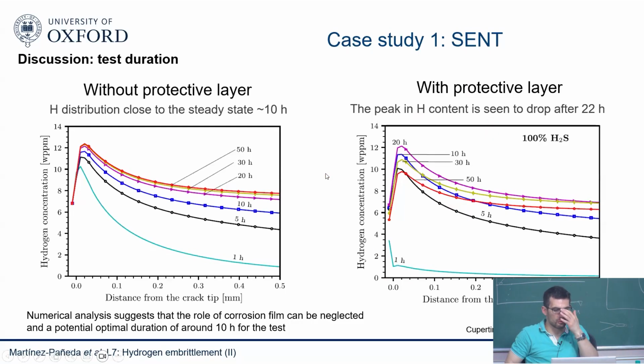So if we think of just hydrogen transport, the peak hydrogen concentration is roughly attained after 10 hours. After 10 hours, if you assume that the H2S is not creating the oxide film, then it will increase a little bit, but very little. And if you assume that it's creating an oxide film, it will increase a little, but then it will go down. So we see roughly 10 hours seems to be the right time instead of 700 hours. But we still see some failures experimentally slightly after 10 hours, so we still need to figure out what happens.